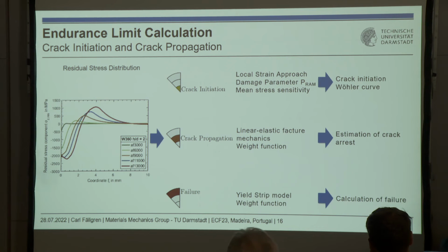So to calculate the endurance limit, you need to take into account that you have the crack initiation, and first you have to calculate that, and you will do it with a local strain approach. We did it with a damage parameter PRAM, which basically is the damage parameter by Smith, Watson, and Topper, but with an additional factor taking into account mean stresses by Professor Bergmann. So we get a crack initiation Wöhler curve.